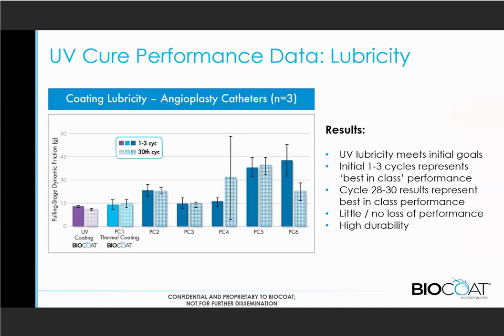So I mentioned maintaining that best-in-class performance. I also mentioned that we had done some work with angioplasty catheters, so I wanted to show that here together. What we did here, similar to the neurovascular catheters, is we looked at 6 different angioplasty catheter brands. One of those actually had a Biocoat coating on it. The other 5 did not. Again, we put them through their paces on the friction testing, and you can see that there are some large differences here.